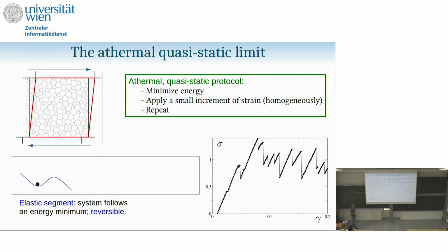And how do you do that in practice? So you take your favorite system, you minimize the energy, and then you apply a very small increment of strain. And we will come to how small is small. So you apply a small increment of strain and repeat. Extremely simple. You minimize, strain a bit, and re-minimize. So what happens when you do this is that, as I explained, when you have a local minimum, in general, a local minimum is surrounded, and this is topology, this is catastrophe theory, every local minimum is surrounded by a basin which has a finite volume, except when the minimum becomes unstable, which are really singular points.